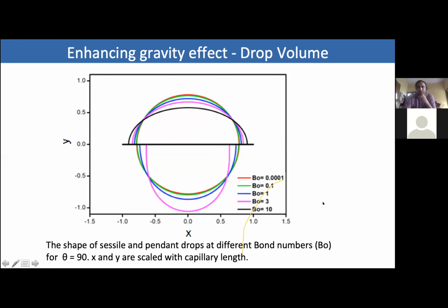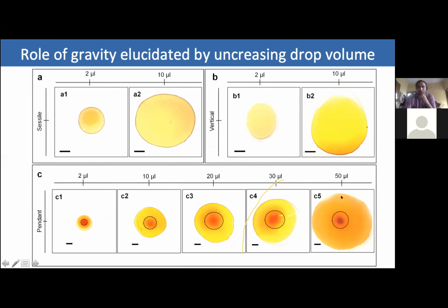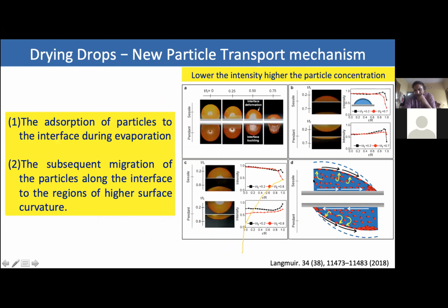And this deformation of the drop leads to what are called drop deformation mediated processes. That means the particles can adsorb to the interface, and they can move along the interface, and either deposit at the edge, or they can move along the interface and then deposit at the center, depending upon the curvature of the drop.